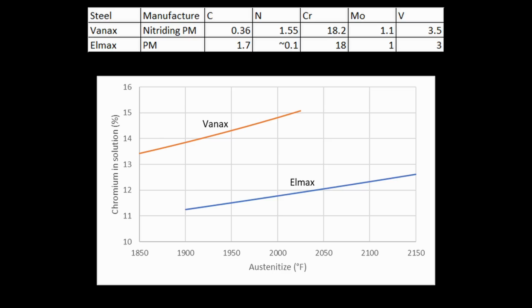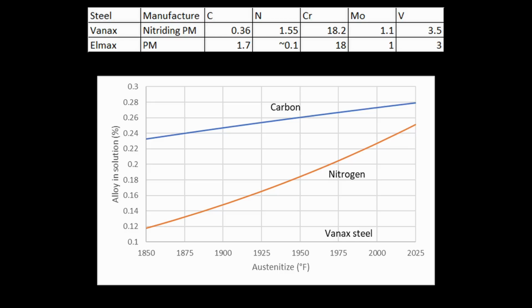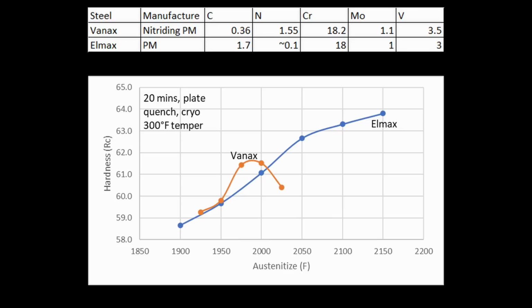So in this case, the chromium in solution is definitely a factor. Elmax, despite having the same chromium at 18%, has much less of that in solution, which means less retained austenite in the Elmax, and it can get to higher hardness. But then we also have the nitrogen factor again, where Vanax gets a lot of its hardness from nitrogen. So that plus the high chromium in solution means that it peaks in hardness at a much lower point than the Elmax does.